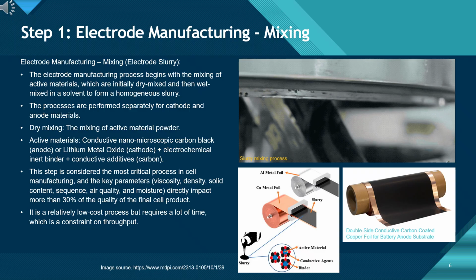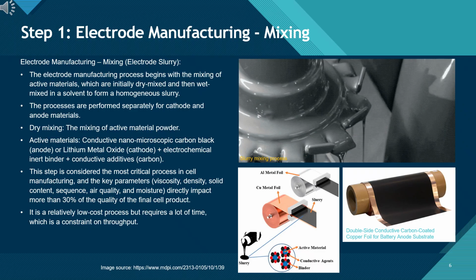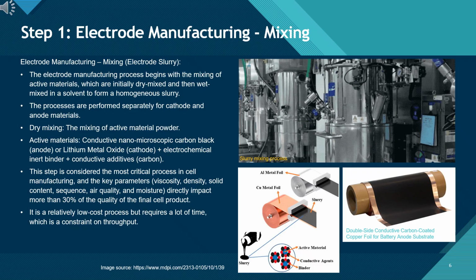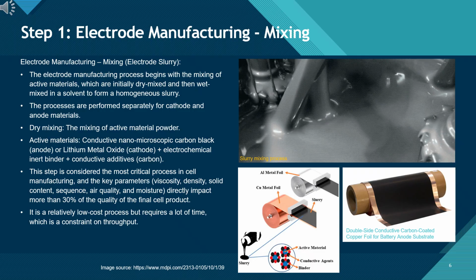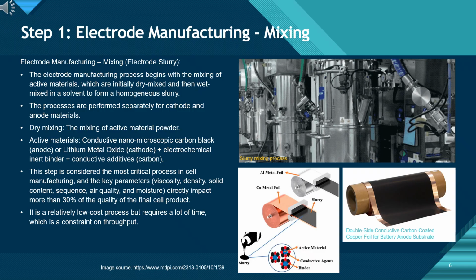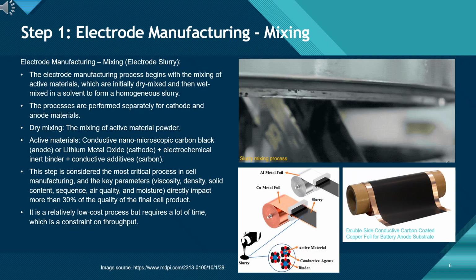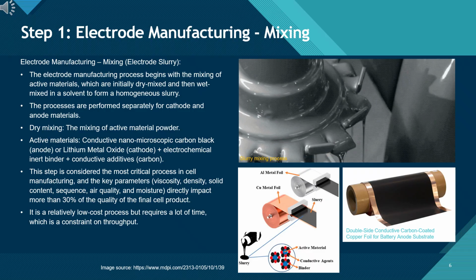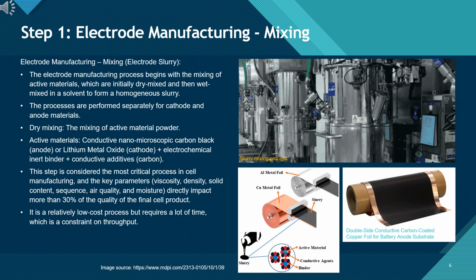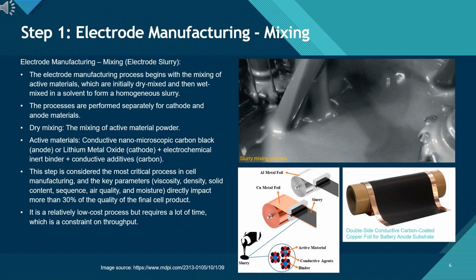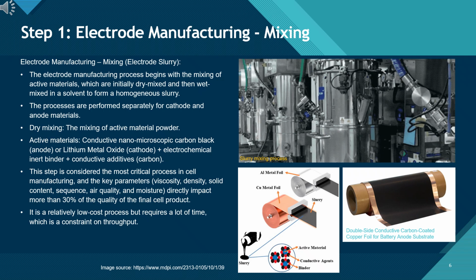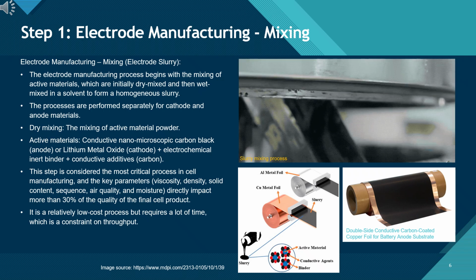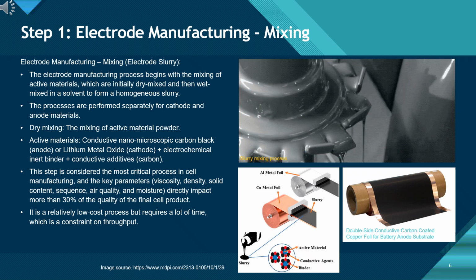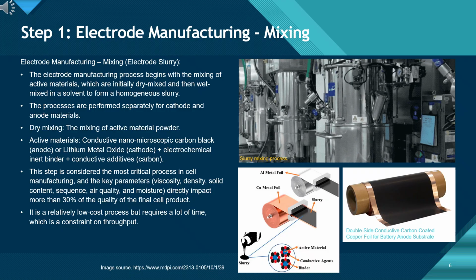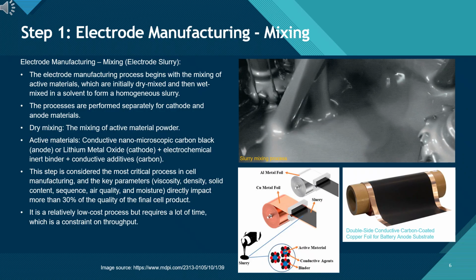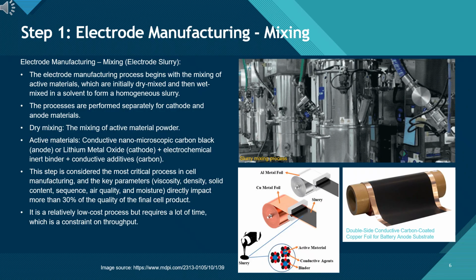Electrode manufacturing, mixing, electrode slurry. The electrode manufacturing process always begins with mixing. Here, the active materials are blended into a uniform slurry. The process starts with the dry mixing of powders. For the anode, that's usually graphite with conductive carbon black. For the cathode, it's lithium metal oxide powders. In both cases, binders and conductive additives are also included to hold everything together and improve electrical conductivity.